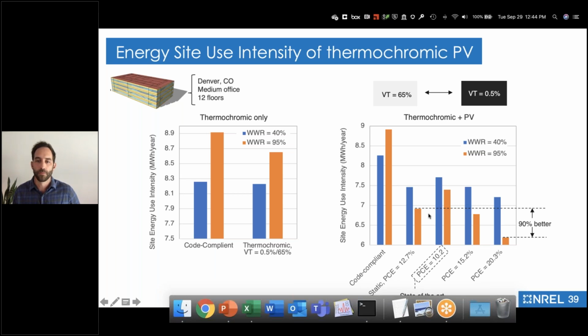And so if we do this, and you increase your efficiency from 10% to 15% to 20%, and again, we can go to higher efficiencies here because we're absorbing more light. That's always the problem here, and I illustrated all the challenges with designing a PV window, because you have to let some light through. If you switch between a dark state and a light state, you essentially bypass that need to balance how much light goes through that you have in a static photovoltaic window, and you have this sort of new paradigm for a switchable or thermochromic photovoltaic window. The thing I want to point out, there's a step change by going from double glazed windows to low-E of that 80% that I showed in the last slide, and then from low-E to a static PV, a step change of something like 80 to 90%.